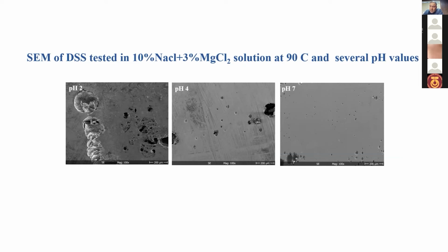The duplex stainless steel micrograph in this figure, from the scanning electron microscope, indicates that the pit initiation frequency increases with the pH reduction. And this is because low pH solutions accelerate the corrosion by providing hydrogen ions, and the hydrogen attacks and damages the surface of the steel and increases the corrosion rate. The pitting formation is influenced by many factors, such as the presence of a highly corrosive film containing chloride compounds, because negatively charged chloride ions migrate into the pit to balance the positively charged metal ions.